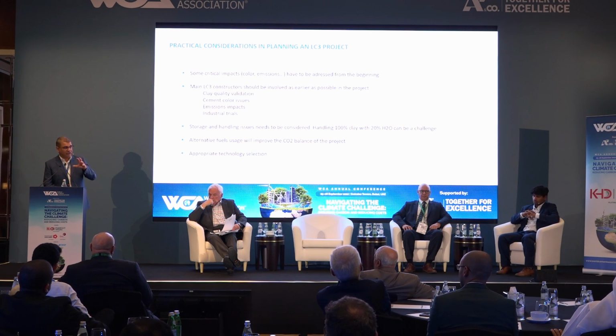The second thing is that we have to approach the constructors of the LC3 projects very early in the projects, because the clay quality has to be validated, because there are some color issues that arise with the LC3. And these color problems can be addressed in the process of the clay calcination if they are taken into consideration from the beginning. There are also some emission impacts depending on the content of the clay. If there are organics in the clay, we can expect to have CO2 emissions in the stack. And also because the contractors have pilots, and these pilots are very helpful to perform industrial trials.